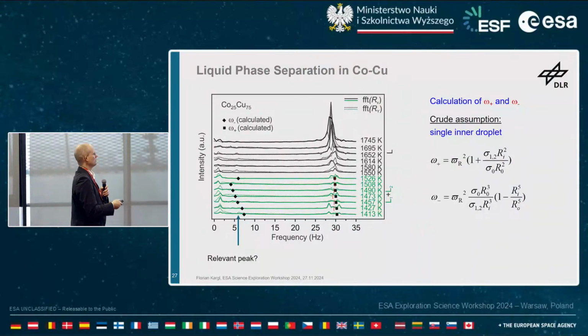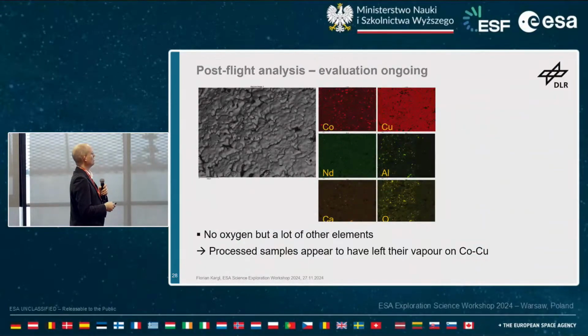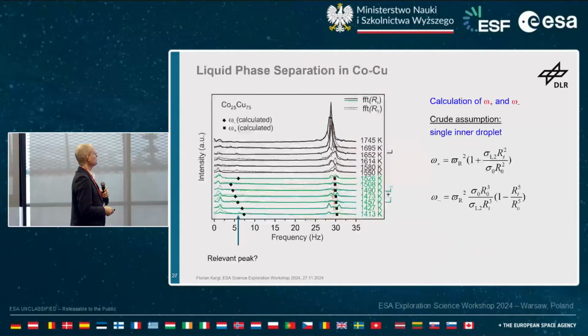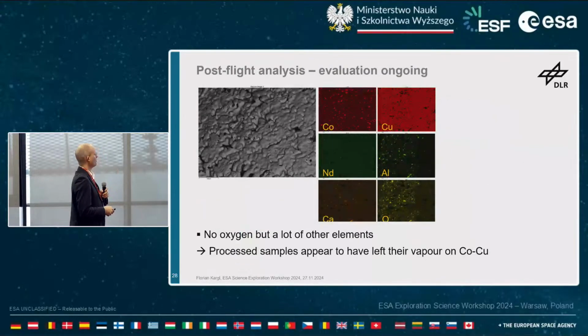So the question is, what is the problem here with this sample? One idea was perhaps oxygen contamination, but that can be ruled out from the post-mortem analysis of the sample, so there was no oxygen inside. However, what was found was a lot of other stuff. This is stuff that came from the other samples, basically evaporated and then somehow stuck on the cobalt-copper, and that might also explain why there were difficulties with undercooling. Analysis is currently still ongoing, so it's not so easy to understand and describe this.